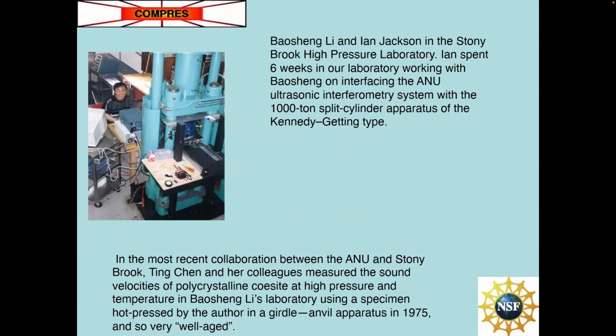Okay. As I mentioned before, Jackson spent 6 weeks in Stony Brook helping Baosheng interface his ultrasonic interferometry with the 1,000-ton split cylinder apparatus of what I call the Kennedy Getting type. The Kennedy is for the press. Getting is for the fact that when we acquired this press from the chemistry department, Yvonne Getting was kind enough to come around and help us clean up the press and activate the pressure system so we could use it, and then we installed the Walker type module inside there. So we guess we should call it the Kennedy Getting Walker apparatus.